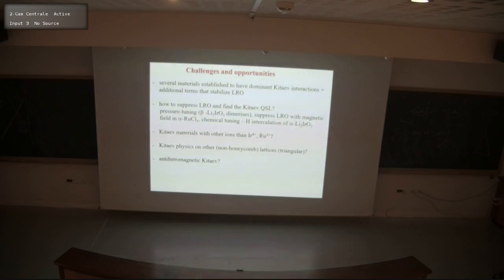Just to finish off, I showed you experiments on a range of materials. They all have dominant Kitaev interactions, which is quite remarkable given the very specific conditions that you actually need to realize this quantum frustration. But all of them have additional terms that stabilize long-range magnetic order, in the form of Heisenberg, further neighbor couplings, or gamma terms. One question is how to suppress this long-range order and whether we'll be able to find the much sought Kitaev quantum spin liquid. Ideas explored experimentally include pressure tuning. You might think that via pressure you change the angles between the bonds, and if the exchange is very sensitive to that, then some of the ratios could change and potentially stabilize the spin liquid.